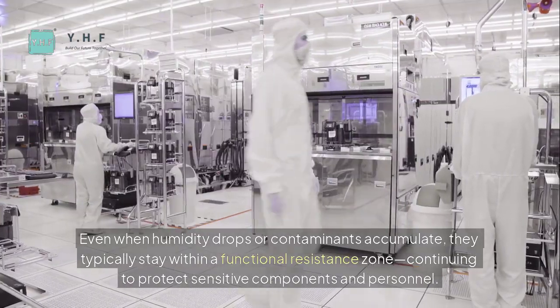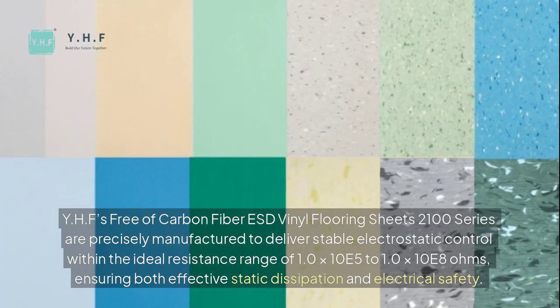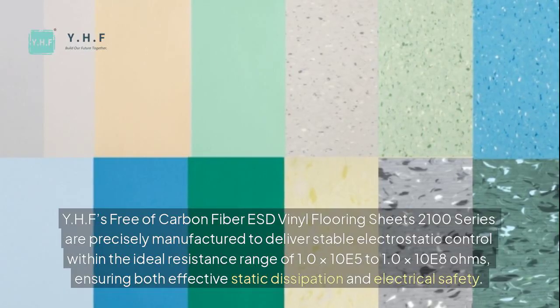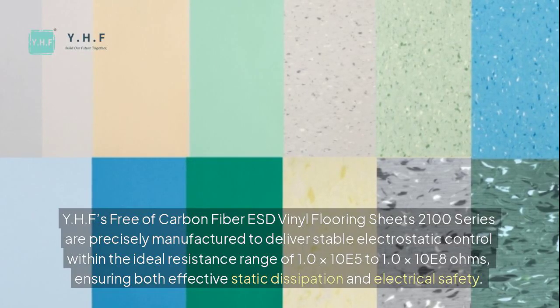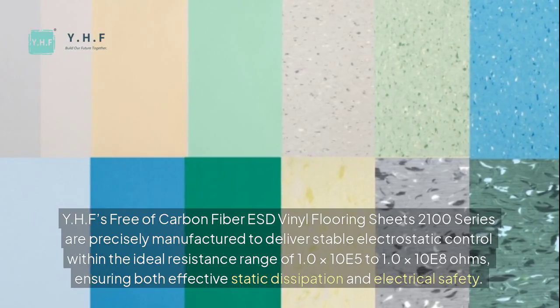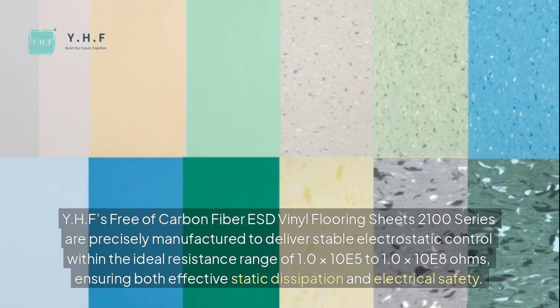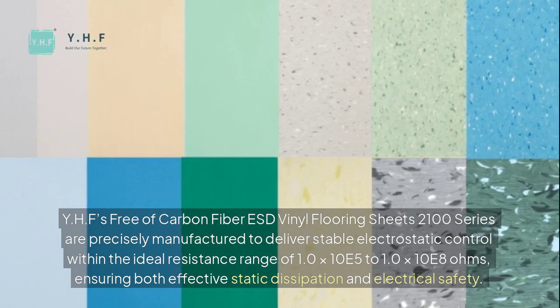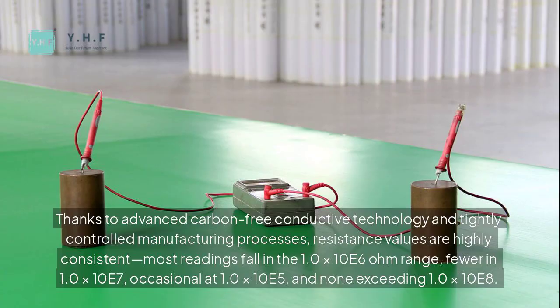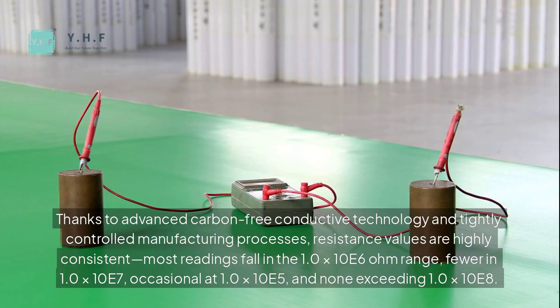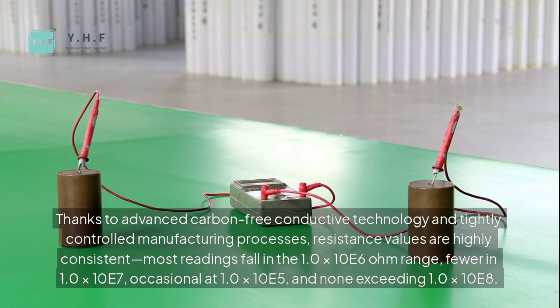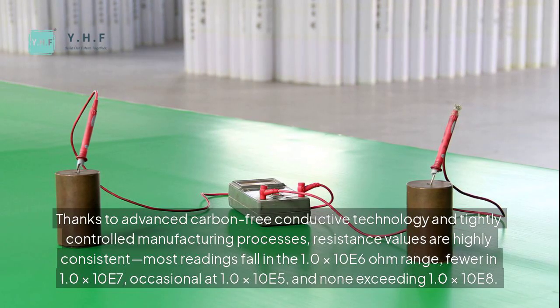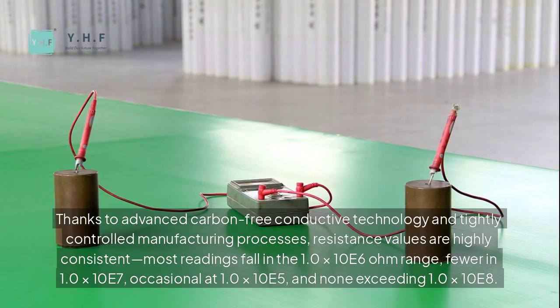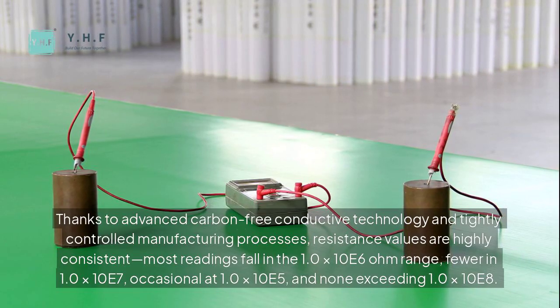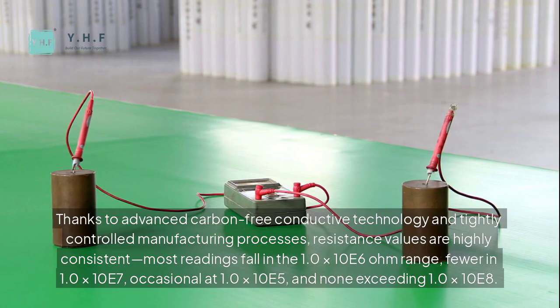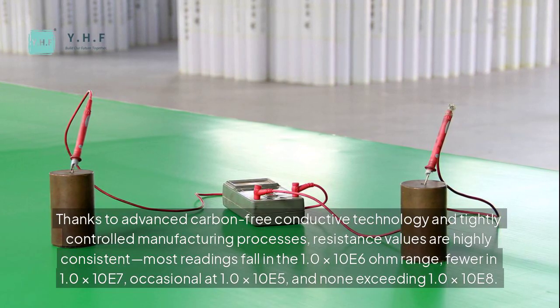and personnel. YHF's carbon-free ESD vinyl flooring sheets, 2100 series, are precisely manufactured to deliver stable electrostatic control within the ideal resistance range of 1.0 × 10^5 to 1.0 × 10^8 ohms, ensuring both effective static dissipation and electrical safety. Thanks to advanced carbon-free conductive technology and tightly controlled manufacturing processes, resistance values are highly consistent. Most readings fall in the 1.0 × 10^6 ohm range, fewer in 1.0 × 10^7, occasional at 1.0 × 10^5, and none exceeding 1.0 × 10^8.